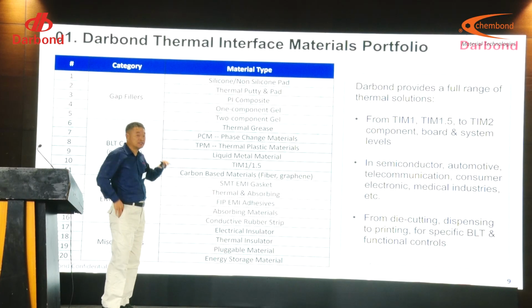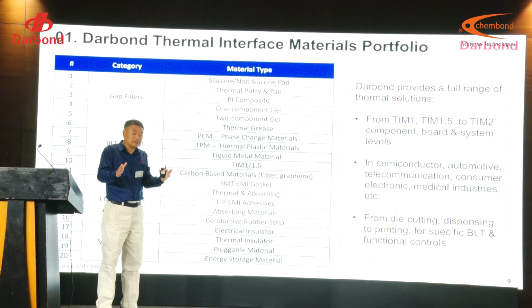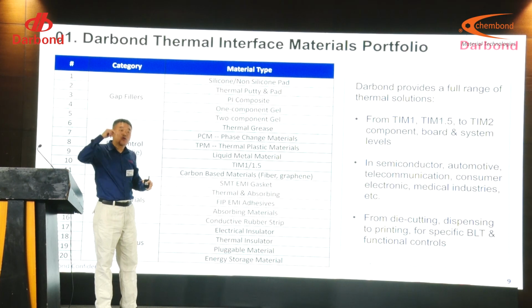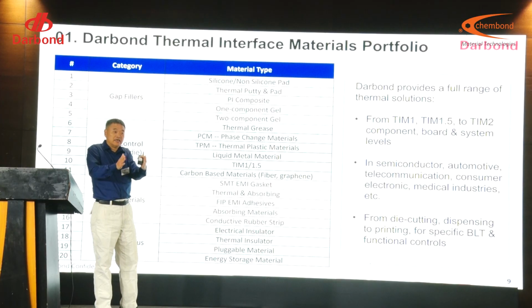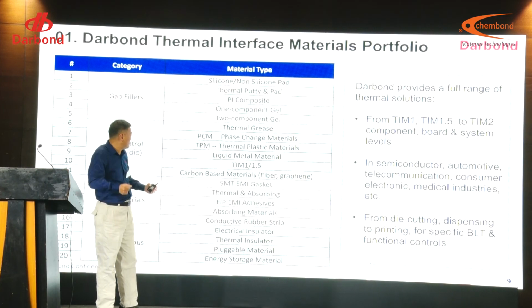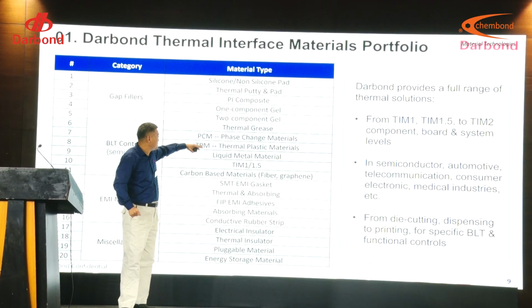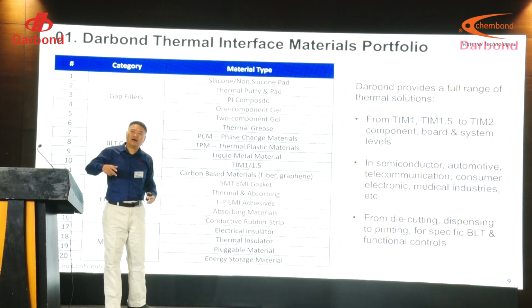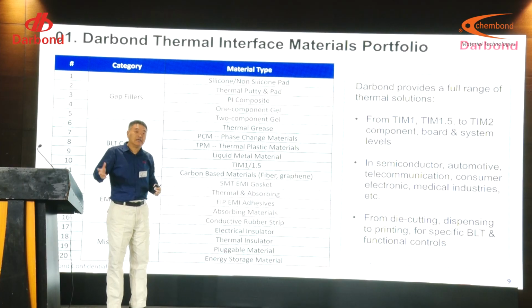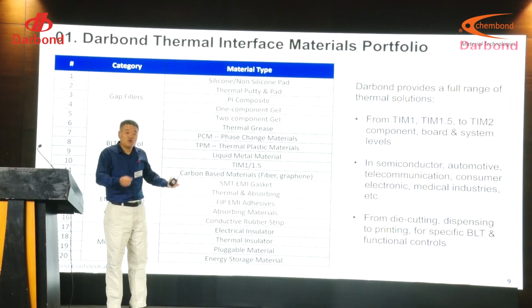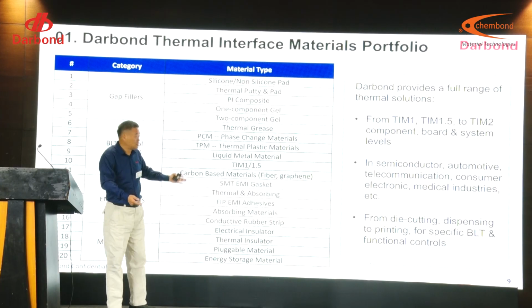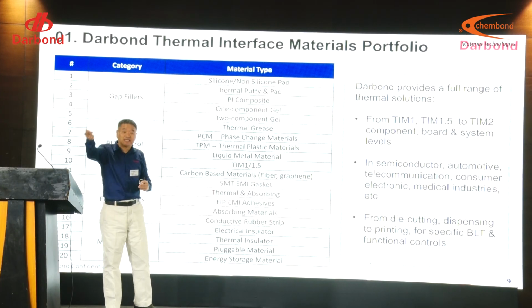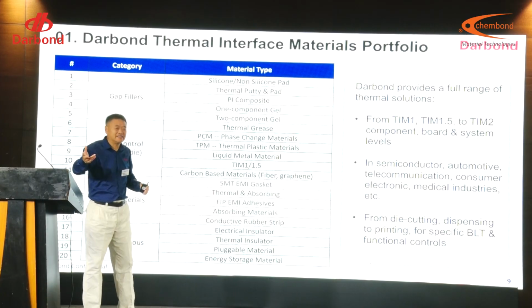For thermal grease, because of large pump out, what we do is cross-link it about 15%, to prevent pump out for the large die. The larger the die, the higher the pump ratio. And also for phase changing materials, this is because the liquid pumps out. So how can we reduce the liquid behavior? We put some plastic in it, so we gradually change the viscosity and it becomes a paste.